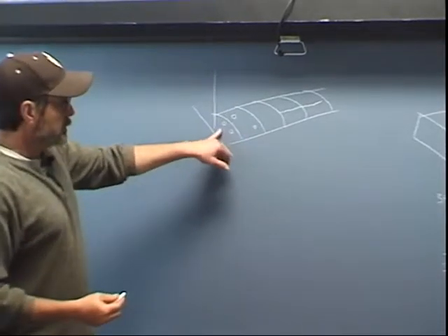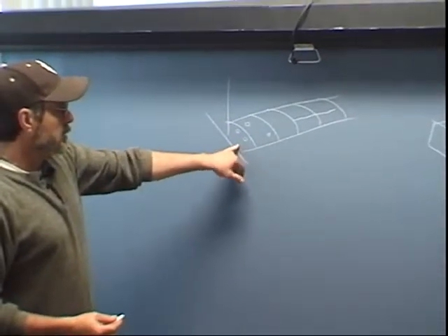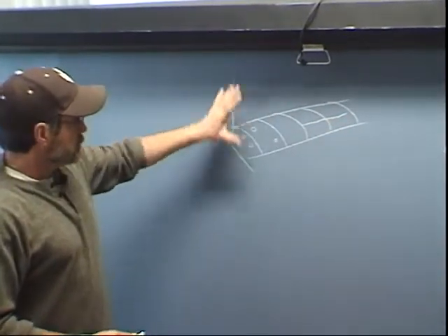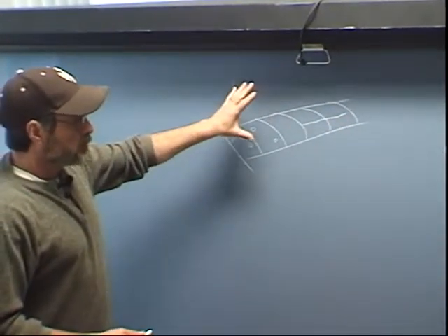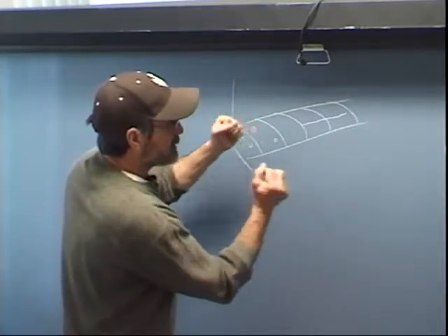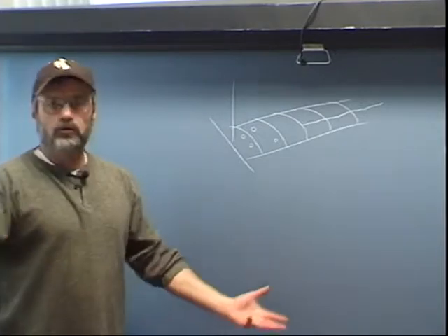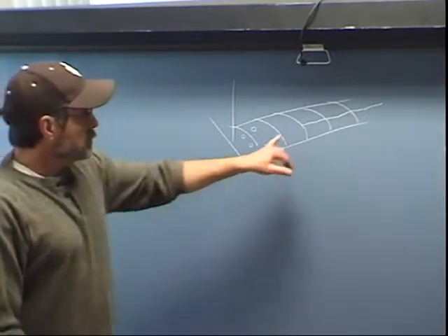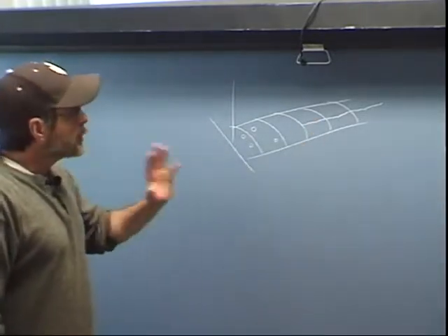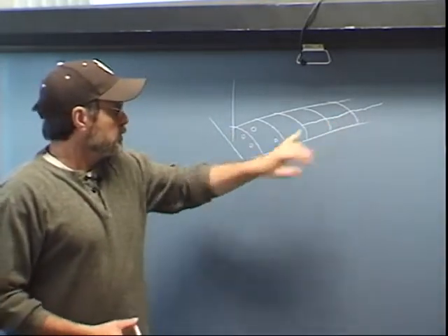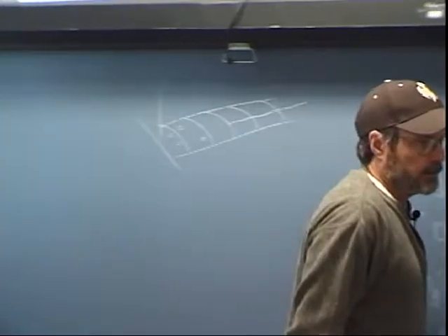Because these are rounded indications, they're not likely to propagate, but this is a linear indication, which if we put this weldment under vibratory stresses, that repeated cyclic pounding on that will make that crack grow until ultimately it will fail. So that's probably the number one criticality consideration: its end condition, and whether it's linear or nonlinear.